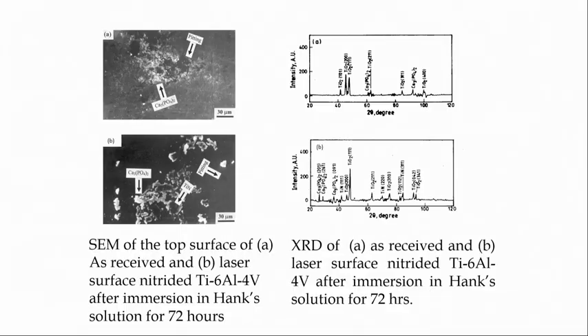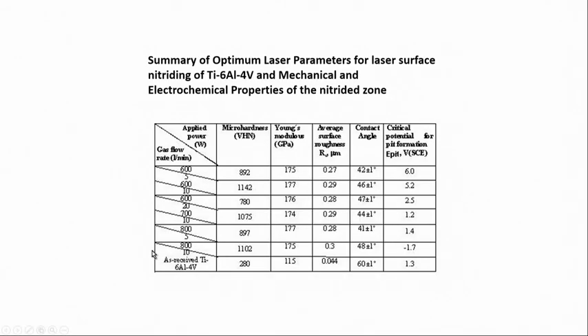And interestingly, this nitriding operation was also aimed at improving the bioactivity of the titanium surface. So, we tried to see the bioactivity behavior by immersing it in Hank's solution and subsequently measuring the calcium phosphate deposition rate at regular intervals. We find that on the nitrided surface the deposition rate was much higher than that of the as-received surface because of its roughness, as well as because nitride also promotes bone growth. So, finally, we ended up with optimization of the process parameters to have the desired results in terms of contact angle, corrosion resistance, and Young's modulus.